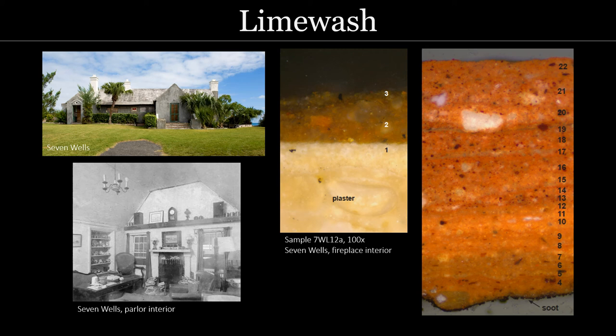But these lime washes were often pigmented, almost always with earth pigments. So these would have been able to withstand the very alkaline environments of the lime washes. And this is one example taken from the interior of a dwelling called Seven Wells. This sample was taken from the inside of the parlor fireplace. And we found many, many layers of deeply pigmented brown, yellow, red, orange, and pink lime washes.